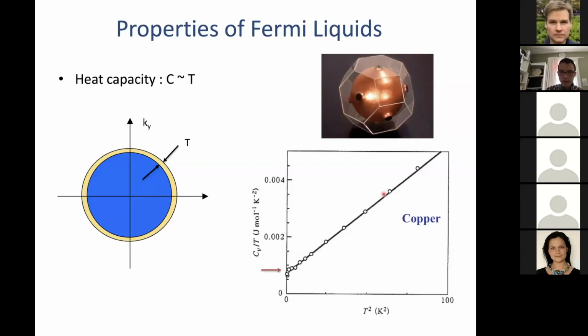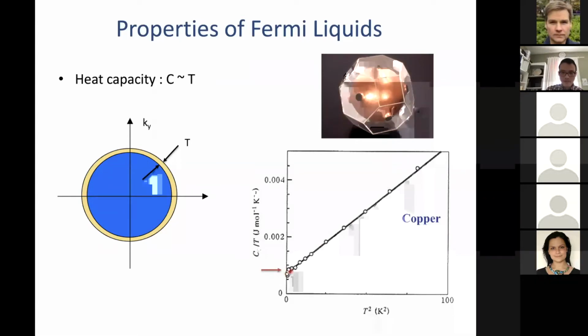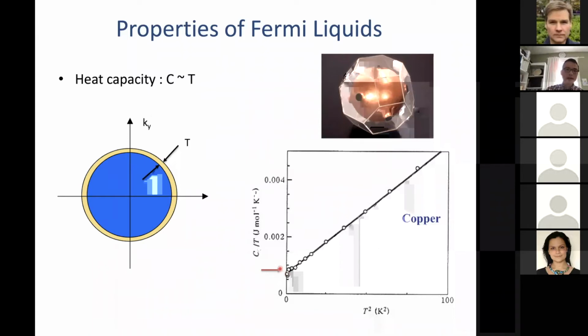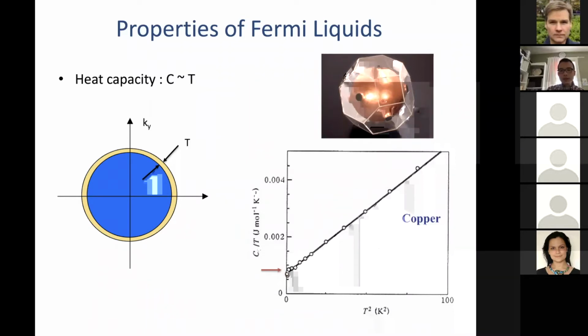And here is a heat capacity measured for copper metal. Here you plot C over T versus T squared. So this straight line is a T cubed contribution to the specific heat that comes from the lattice vibration. But what we care about now is this finite intercept here, which measures the fermionic contribution to the specific heat. And this picture here shows the shape of the Fermi surface for copper. The thing is made of copper.